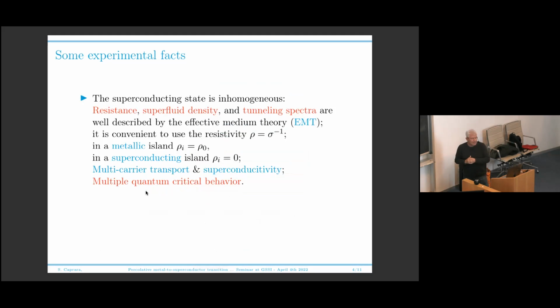So we think, and I will discuss maybe some of these results, that the superconducting state in this system, in these interfaces, and then we found out also in many other systems, but I will take these interfaces as a paradigmatic example, is inhomogeneous. I will show you that the resistance, the superfluid density, and the tunneling spectra are rather well described within the effective medium theory. When discussing the metal to superconductor transition it is much easier, and this comes at no cost, to use the resistivity instead of the conductivity.